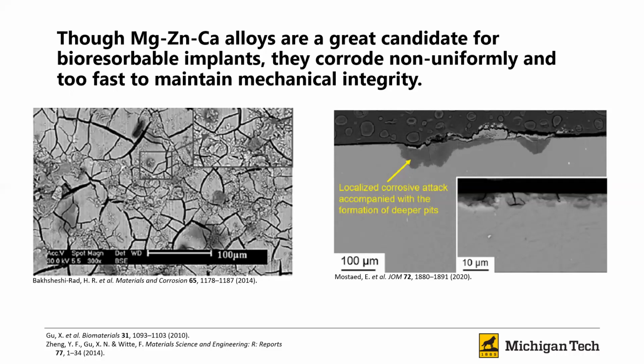So as you can see here, they corrode too fast because of the presence of coarse precipitates that are formed when zinc and calcium are added to a magnesium matrix. And since they have a higher electrochemical potential, they will corrode preferentially, causing localized pitting and cracks, as you can see here in these two micrographs, that will compromise the mechanical integrity of the bioresorbable implants, causing them to fail earlier than the bone has healed.